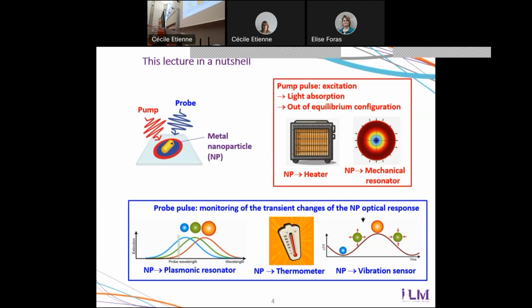And to follow temperature evolution, to follow vibrations, that's the role of the probe pulse. The probe pulse will exploit the fact that the nanoparticles have an optical response which is resonant. They are plasmonic resonators, and this response is affected by heating or by vibrations. So following the change of this optical response after initial excitation, the probe beam will play the role of a thermometer or of a vibration sensor. That's the key idea of my lecture that I will describe in more detail in the following.